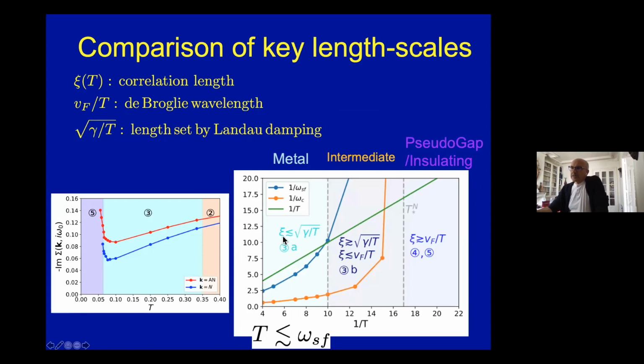There is a regime where psi, the correlation length, is smaller than the scale associated with the Landau damping. This is actually the metallic regime. There is a low temperature regime where psi becomes larger than the thermal de Broglie wavelength. And that is the criterion for the opening of the pseudogap. And what we checked in these computations is that indeed these various regimes are very well delimited by this criterion, comparing psi to both the Landau damping scale or the de Broglie thermal wavelength.